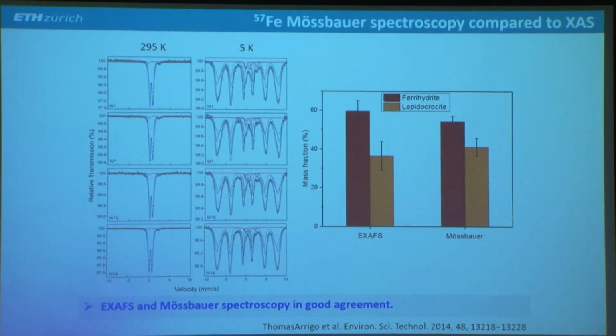And these are some Mössbauer spectra at room temperature and 5K. And I just want to summarize the result here and compare it with the EXAFS data. So this shows the ferrihydride and lepidocrocite mass fractions determined by EXAFS, and this is by Mössbauer spectroscopy, and they agree very well with each other. So I think this was actually a good confirmation that indeed it's lepidocrocite. And what this means is that this lepidocrocite in these samples is extremely nanocrystalline. It's so nanocrystalline that it cannot be detected by X-ray diffraction. But it's clearly different than ferrihydride, and you will see later that it has a different reactivity.